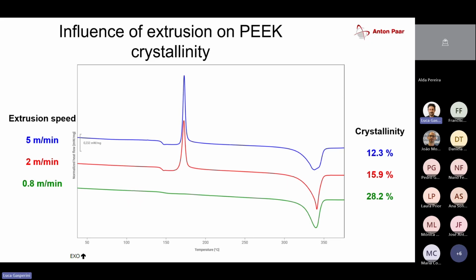And then, of course, at even higher temperatures, we see the materials melting. However, the one sample that was extruded at the lowest extrusion speed only shows me the glass transition, which is not very pronounced, again very weak, but I see no cold crystallization. So this extrusion speed is slow enough for the polymer to crystallize during the cooling process.